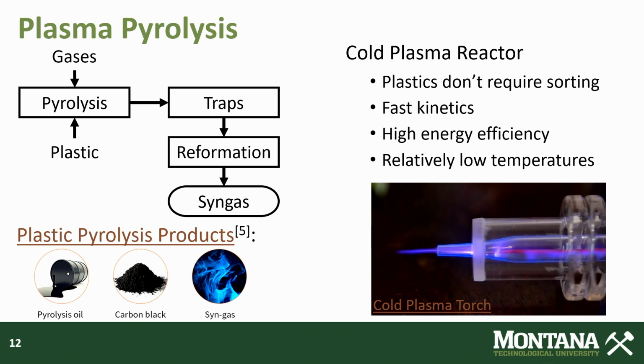So we can get pyrolysis oil, which is an intermediary step to produce fuels, but it does add an additional cost because it has to go through a distillation process to obtain the oil. We can get carbon black, which is used as a reinforcement in tire and rubber products, as well as an additive in plastics, paints, and inks. And what we're really looking at is this syngas for our application. So syngas is used in smelt reduction technologies to produce molten iron and direct reduction of iron from iron ore processing. And the one nice thing about using pyrolysis to do this is that we don't have to use coal or natural gas to generate this syngas.